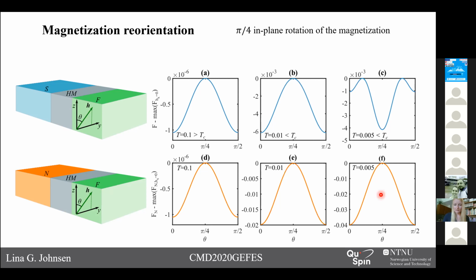Again, we see that if we don't have a superconducting phase transition, nothing happens. Since this effect is weaker than what we saw for in-plane to out-of-plane reorientation, we would expect that we need a stronger shape anisotropy so that the magnetization is enforced to be in plane in the first place.